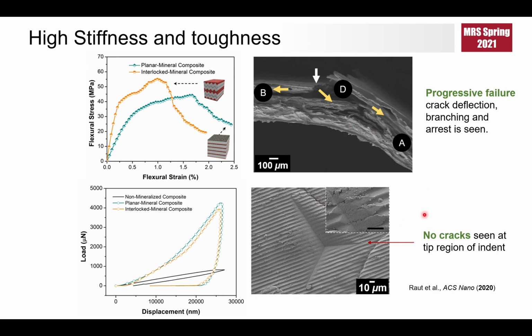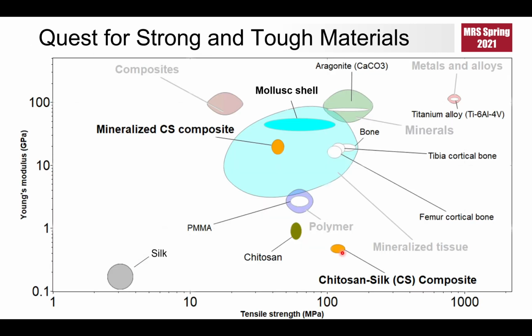Furthermore, nanoindentation on the surface of both the mineralized composites shows that the stiffness of the composites is at least 10 times higher than that of chitosan. Also, the areas around the indentation, especially the corners of the indentation mark, do not show any cracks, thus showing no signs of brittle cracking. So all put together, the interlocked mineralized composite shows a tensile strength and stiffness not only higher than that of the constituent chitosan, but the mechanical properties are also comparable to that of bones.